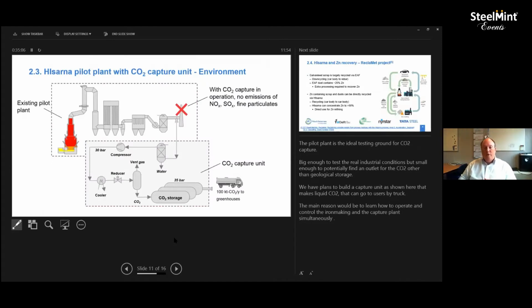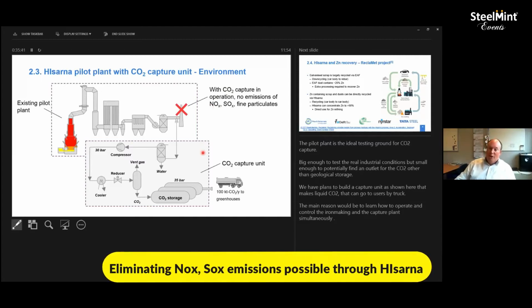Now, then the good thing is that if you build a HIsarna plant that has pretty much pure CO2 coming out of the top of the process, going through its gas cleaning and scrubbing system, and then you feed that complete feed into a CO2 liquefaction plant, you've basically built a plant that has no stack. And if it has no stack, it's not just that you have no CO2 emission, you also eliminate the emissions of nitrous oxide, sulfurous oxide, and fine particulates from the stack. And that is not so much a climate issue, of course, but it's very much a local and regional environmental issue that you can tackle simultaneously with tackling the CO2 emissions.